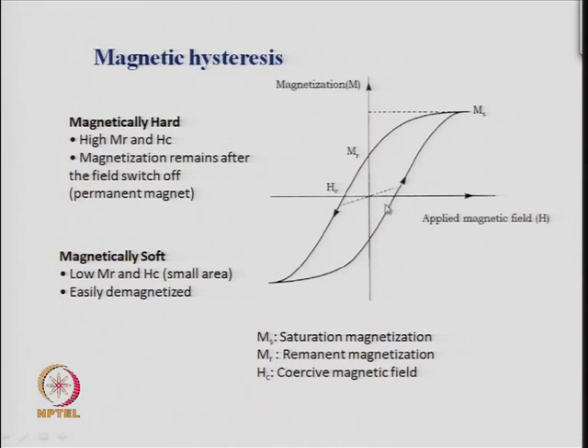Now, if you change the magnetic field in the opposite direction, so you are increasing the magnetic field in the negative direction, then the magnetization will further decrease till it hits the x axis at a particular field. So, you are making the field negative, which means the field has a direction which is opposite to the original direction of the magnetic field. This field which you are now applying is in the opposite direction and has a magnitude Hc when the net magnetization goes to 0. That field at which the magnetization is really 0 is called the Hc or the coercive field.